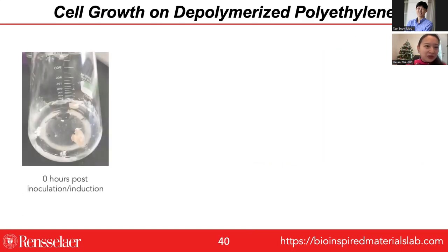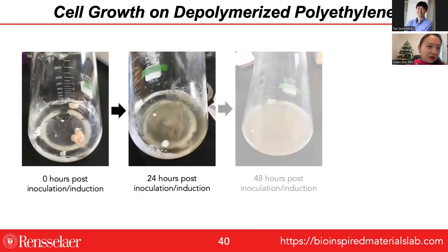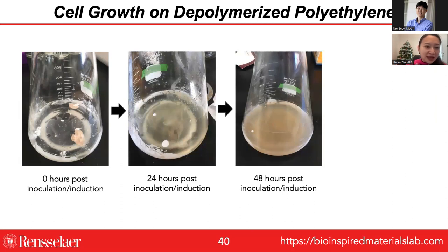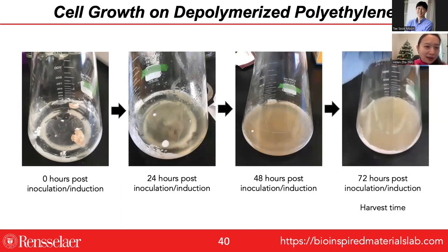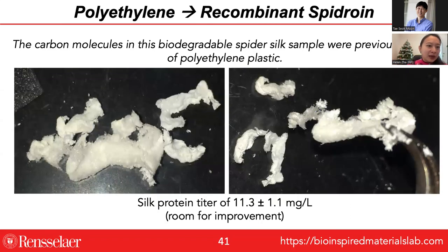But what we were able to see is, first of all, growth of cells in this flask using just this wax from depolymerized polyethylene as a carbon source. And we were able to produce recombinant silk at a titer of about 11 milligrams per liter of culture, which doesn't sound like a lot, but actually that's about the same as what BL21 E. coli, the workhorse strain used for lab recombinant production experiments, produced. So this is, I think, a really good starting point. There's a lot of promise here for us to optimize.